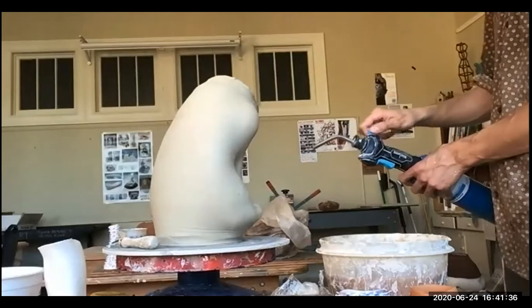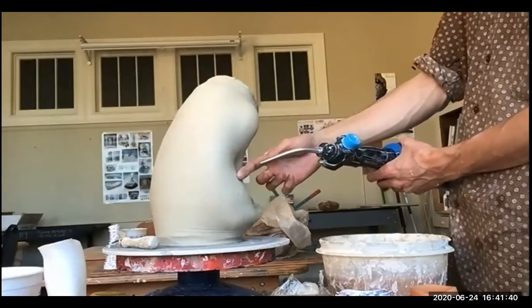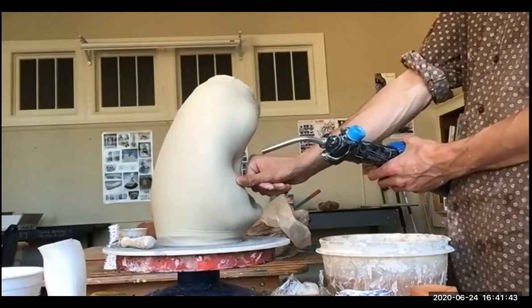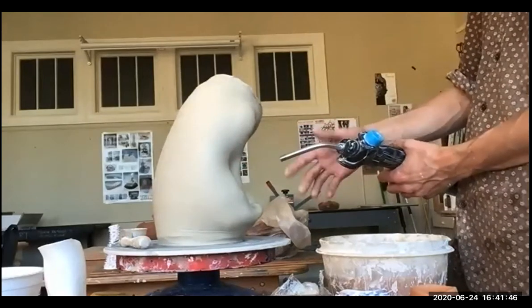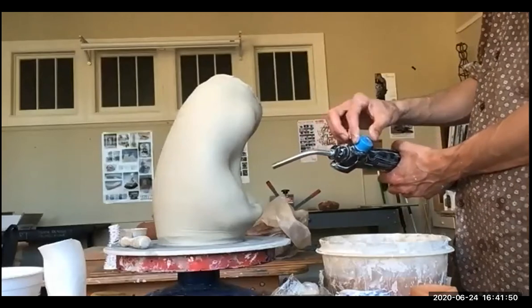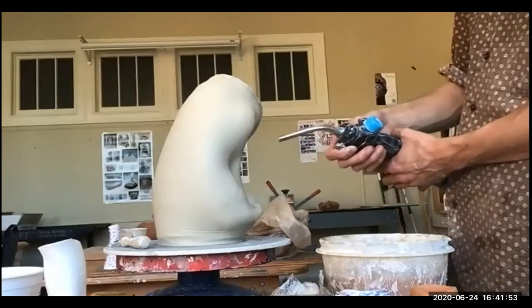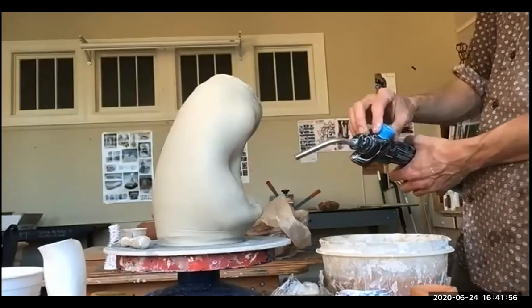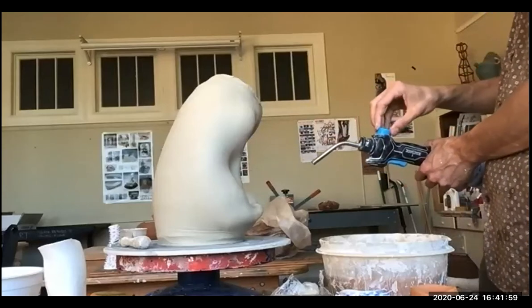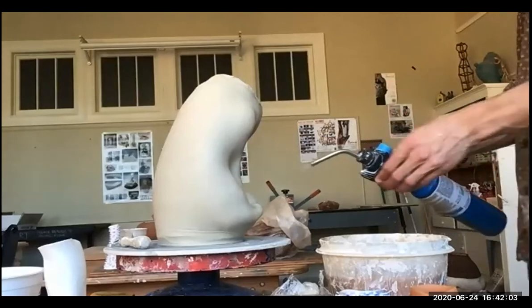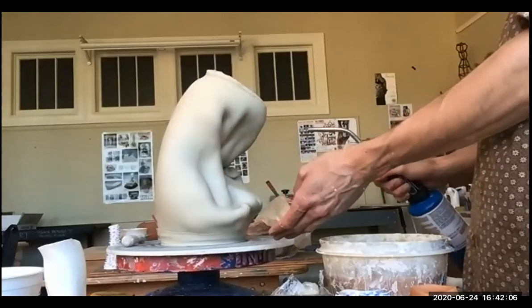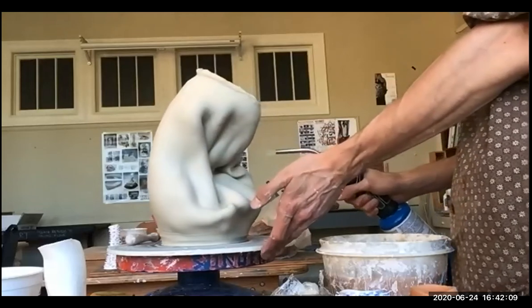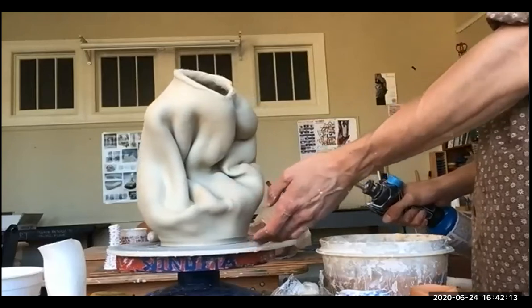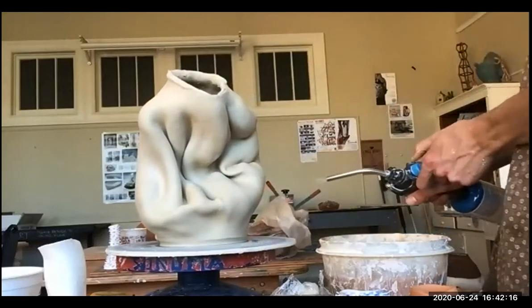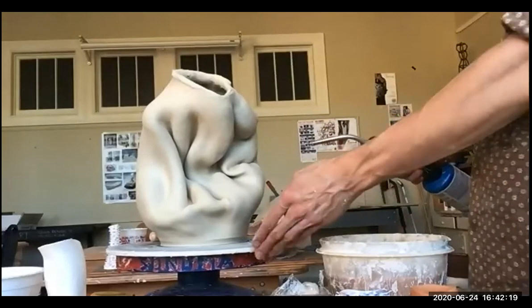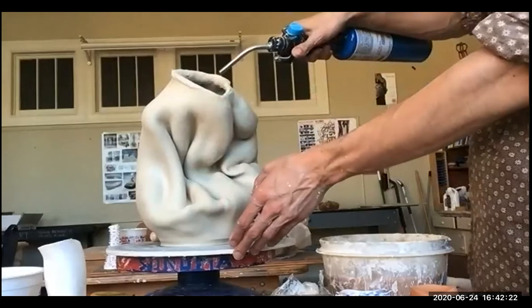Just being gentle. If you keep the blowtorch really close, you'll really scorch the surface, and it'll get bone dry really quick. Then, like we talked about how it wicks moisture from the inside, you'll get the surface bone dry, like if I held it right there, but then if you pull away, water will precipitate to the surface and actually rehydrate it after a little bit. So just trying to be sparing, just a little bit. Maybe a little on the inside.